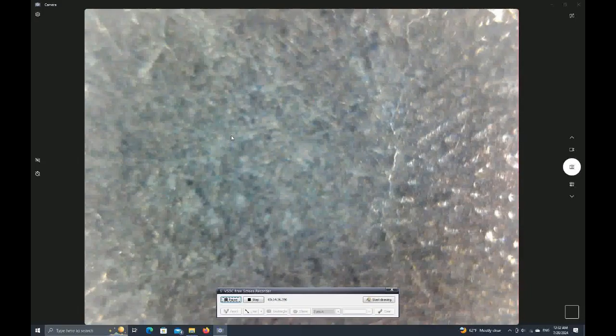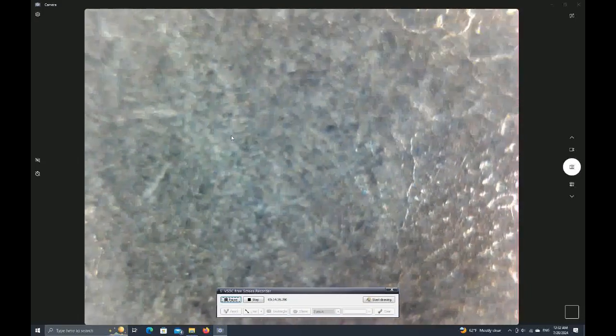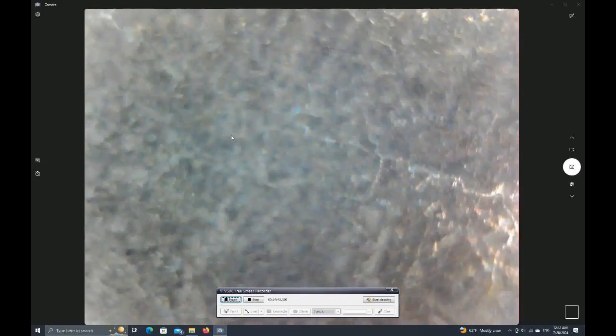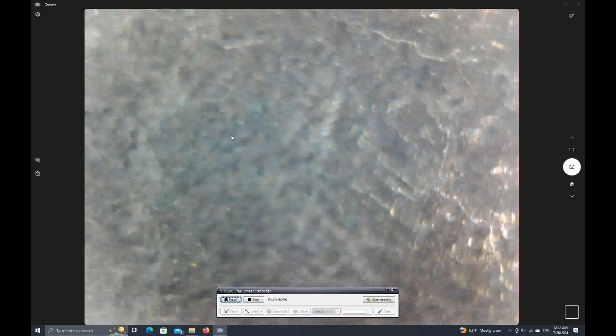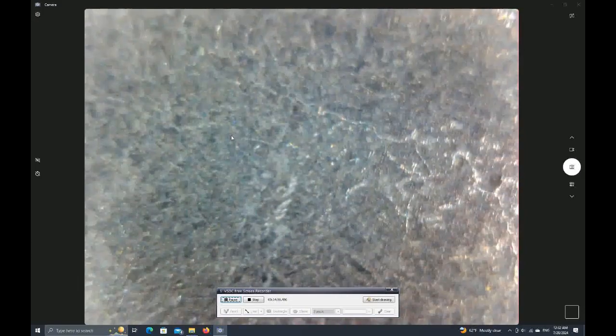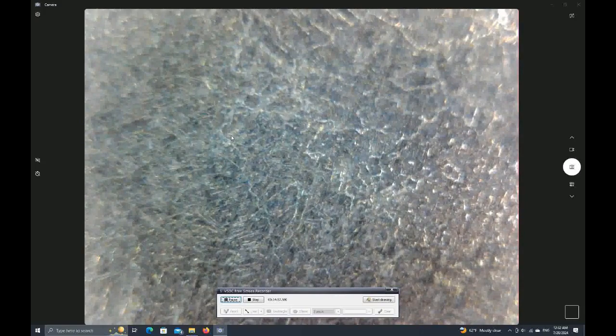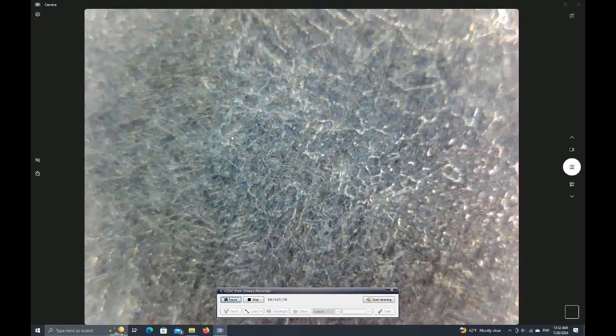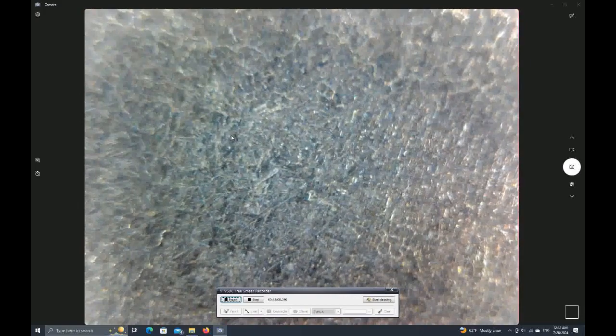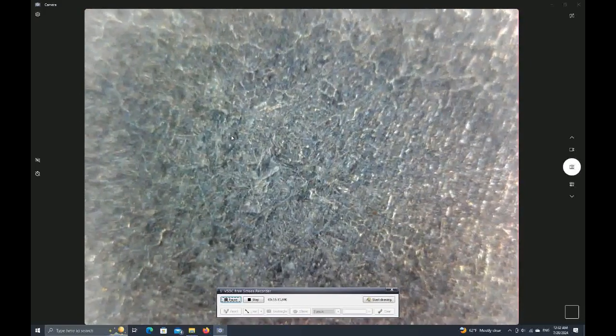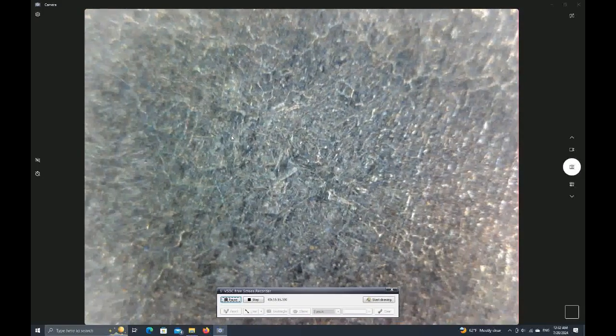And again, as this steel is heated up, if I don't pre-treat it to try and shrink these carbides, I'm going to risk having a piece of steel that would have essentially flaws in it when it comes to forging, where these grain boundaries would become sort of a liquid phase while the surrounding material around them is still solid phase, and I could have an ingot that crumbles, kind of like cast iron. So we'll see how it goes. But we're still seeing, beyond that, some pretty cool features here. Nice crystalline repeating units. And so let's go ahead and take a look at today's ingot under this same level of magnification.